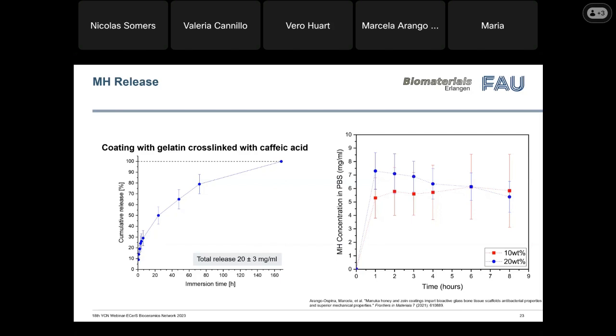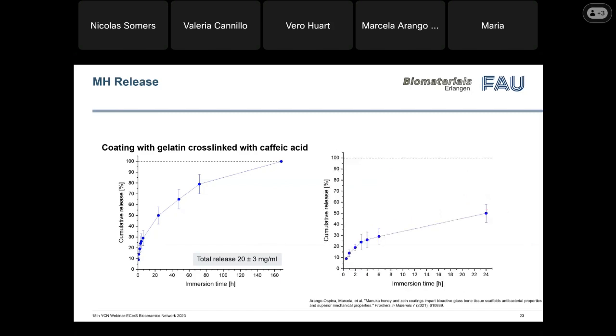It's not anymore that the whole amount is released in the first hour, but here we have a more sustained release, and here we can see the release during the first day. So it's quite different compared to the coating with silane. And here we could also see that it was possible to have a higher amount of honey released from the scaffolds compared to the previous case.